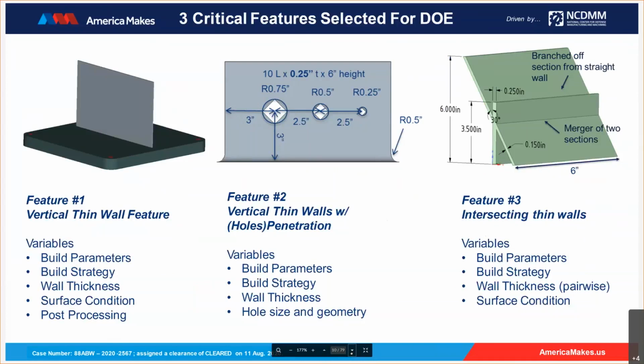So for example, for the thin vertical wall, you can see that it's the simplest out of the three features, where the wall thicknesses and the surface conditions are dependent on the build strategies and the build parameters that are employed. And then we also had some sections of the wall go through the post-processing steps. So the microstructure and the defect structure based on the heat treatments that the part sees was also taken into account.